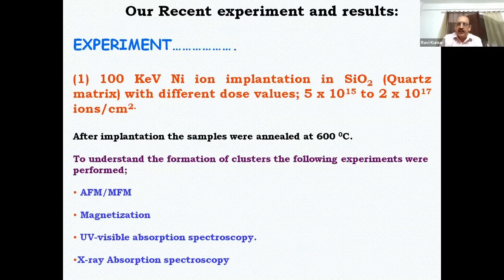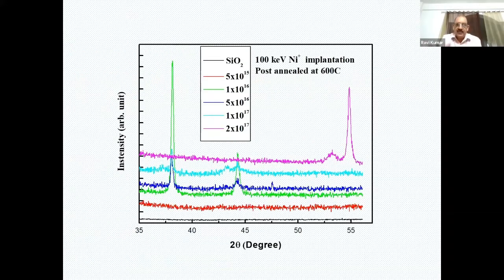First, we did the experiment with the silicon dioxide quartz matrix with different doses of implantation, starting from 5 times 10 to the power 15 ions per centimeter square to 2 times 10 to the power 17 ions per centimeter square. After implantation, we anneal the sample at 600 degrees Celsius, and then we can characterize them.